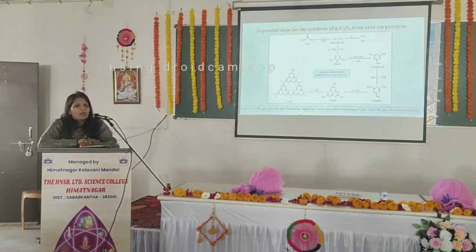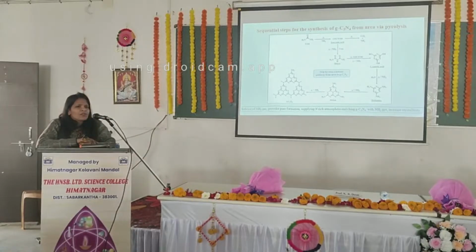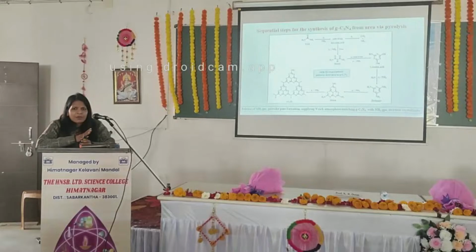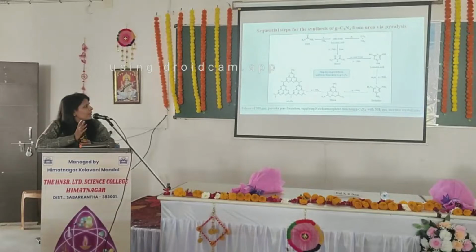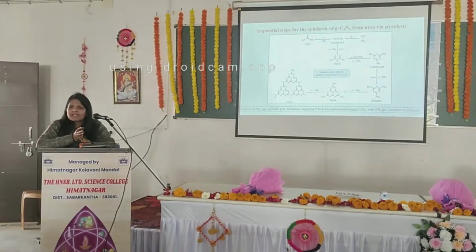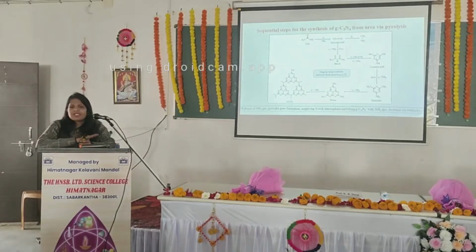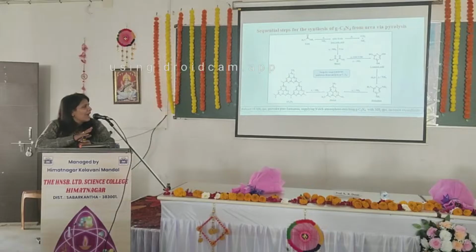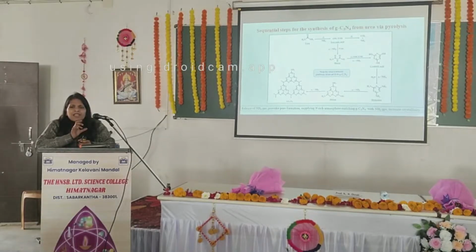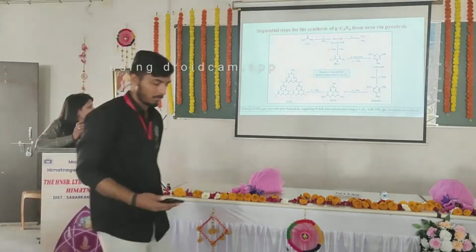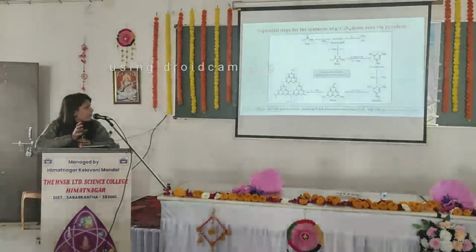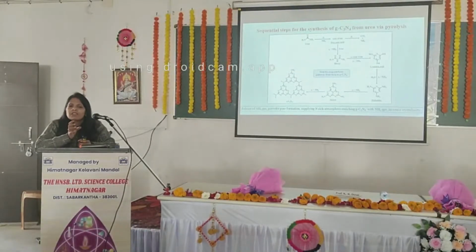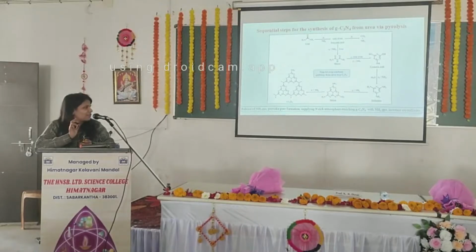This is the preparation method, how the g-C3N4 forms. First of all, urea converts to isocyanic acid, then isocyanic acid converts further, and this is the pathway as proposed in the literature. The important role of urea is that it releases ammonia, creates the pore formation, and supplies the nitrogen to g-C3N4, which is very important for the catalysis step.